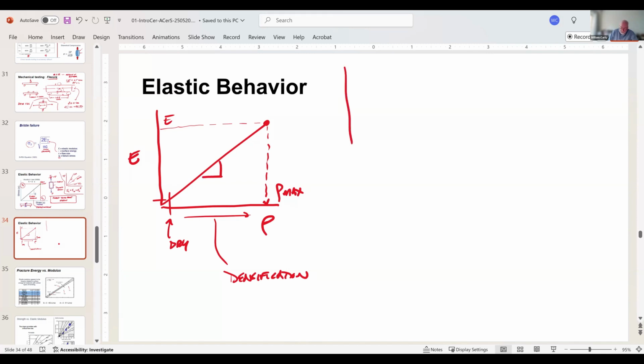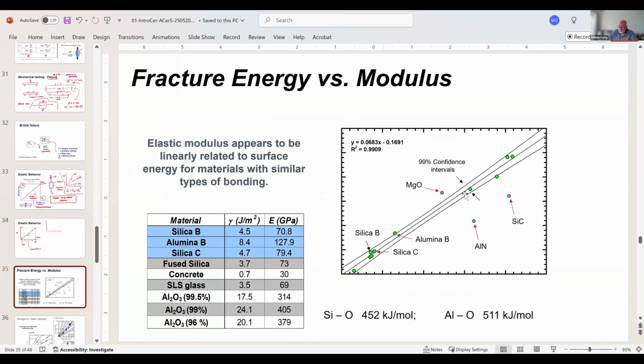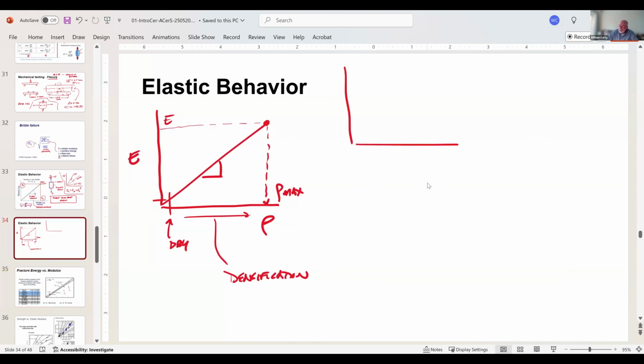Now, we've done some measurements, and I'm going to show you some data for that here. We developed some techniques for measuring fracture surface energy. So recall that I have this relationship. Strength is equal to the square root of 2 times elastic modulus times fracture surface energy over pi c. What I find is that my fracture surface energy scales linearly with elastic modulus in a brittle material. If it's a brittle material, or behaves elastically, when I stress it, it deforms a certain amount based on the load that's involved. And when I release that load, it goes back to its normal position.